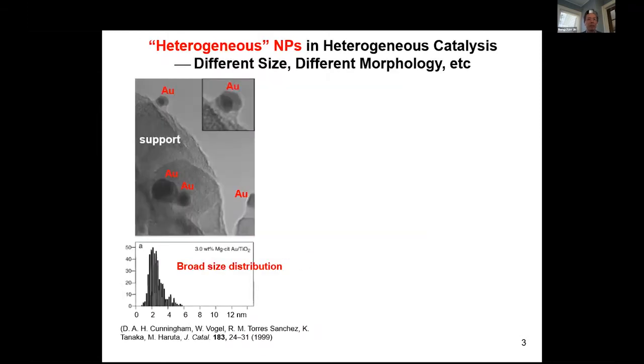So here's a typical TEM image for the heterogeneous catalyst. We have two components. One is those metal nanoparticles, transition metal nanoparticles, and then the second component is the support, the metal oxides like silica, aluminum oxide, titanium dioxide, that you typically use to support the transition metal nanoparticles. So obviously, the most important thing is those nanoparticles, no matter precious metal nanoparticles or non-precious metals. So here, if you run the typical size distribution, you're going to find out that they're actually quite polydispersed. So for practical purposes, it's fine, as long as your catalyst is highly active, highly selective, and highly stable, and you're doing a very good job.